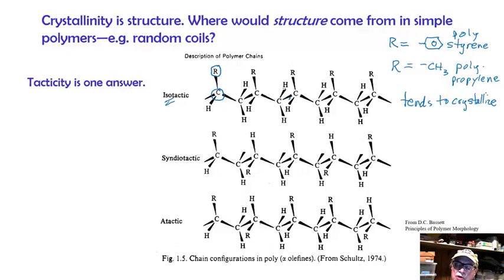I got to the point where I thought somebody had taken a bottle and put some other thing in it. The bottle said polystyrene, or maybe they put Teflon in it or something. I was really curious, so I went back and looked at the bottle carefully, and it was isotactic polystyrene, where all these R groups are the same, and it was crystalline. There is no way to get it to dissolve unless you heat it. And in the solvent I was trying to work with, I couldn't heat it that far. The solvent would have evaporated. So this crystallinity really matters to how the polymers behave.